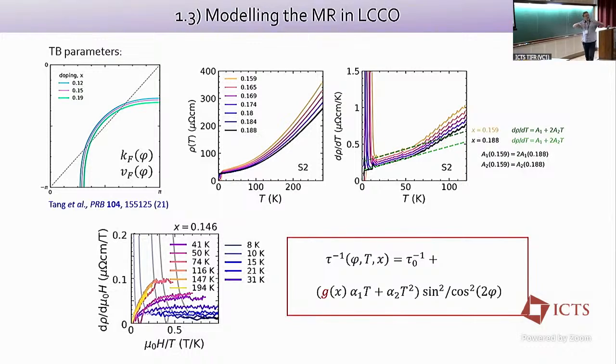Normally when you increase the magnetic field and you've got an anisotropic scattering rate, as the cyclotron motion gets bigger, that anisotropy just gets washed out. But if there are these hotspots, that essentially prevents the cyclotron motion from creating the full orbits, and that gives rise to this linear in-field magnetoresistance. So we also add hotspots, and the position of those hotspots is going to be quite crucial, particularly when we discuss the Hall effect.